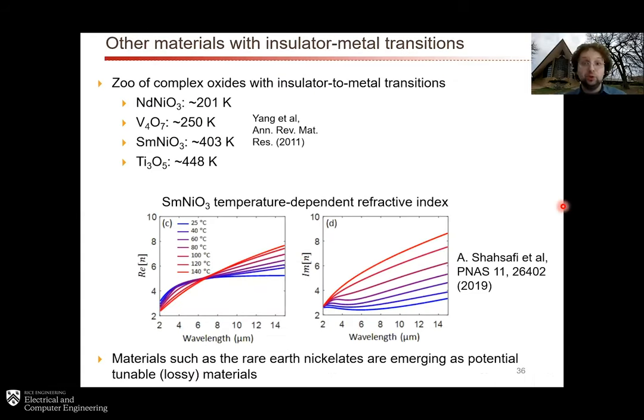There's actually a zoo of complex oxides that have insulator to metal transitions that I think would be very exciting for thermal emission measurement. Just to give you an example from this review article from the Ramanathan group in 2011, there's neodymium nickelate, which has a phase transition at 200 Kelvin. There is this V4O7, this vanadium oxide that has a phase transition at 250. There is this titanium oxide, Ti3O5, that has a transition at 450 Kelvin.